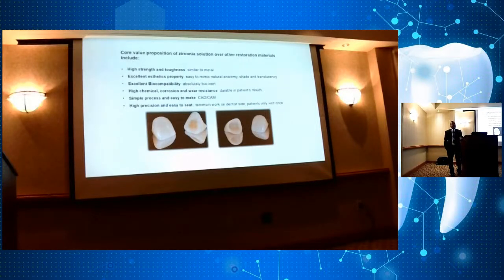And another misnomer is that zirconia has a self-healing property. It does not. It actually is quite the opposite. If you develop these flaws in the zirconia, the dentist grinds on it and you see sparks flying, that is a complete no-no. Okay? At that point, you have to ask your dentist, hey, how much grinding did you do? Oh yeah, I ground it, it was very high, and then I polished it and seated the crown. That crown will eventually fail. It's very unfortunate because the dentist is really not knowledgeable about how to treat this material.